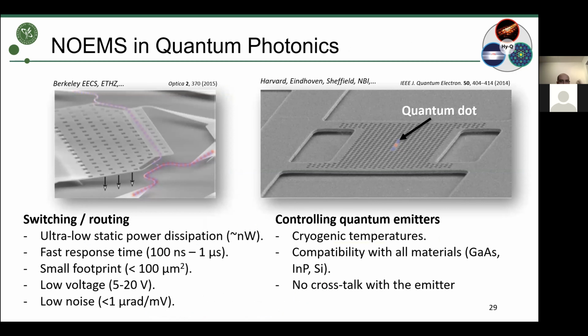So just some examples of works done by several groups on, for example, tuning a beam splitter just by controlling this cantilever. Here you apply an electrostatic force and you move this cantilever up and down, and you can control where the light goes. Here is a photonic crystal cavity that you can tune. So you just move this membrane up and down, and you're tuning the resonance of this cavity. And this has been shown to be also compatible with quantum emitters, which is also very important. So it operates at cryogenic temperature, and it's compatible pretty much with all materials. So it's kind of a material agnostic approach to tuning and reconfiguring devices.